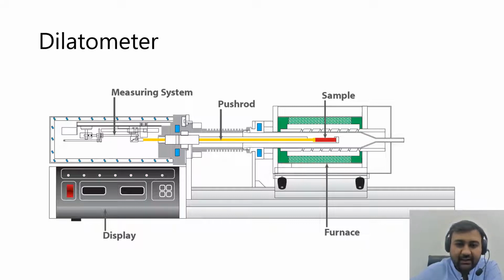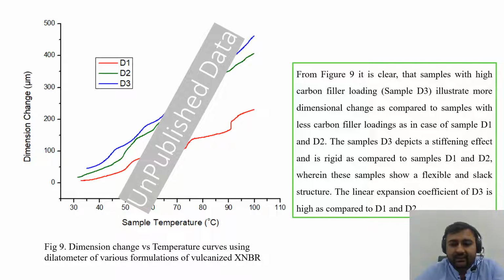Similarly, dilatometer tests were performed. The samples of three different hardness were placed in the dilatometer in a furnace, and the dimensional change was observed with the change in temperature. So these are the results of dimensional change with temperature curves using the dilatometer of various formulations of vulcanized XNBR.